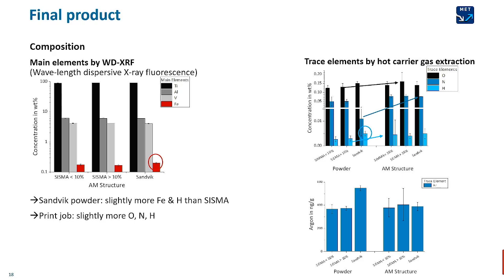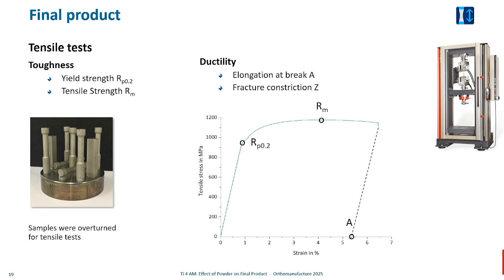And after the print job, we had some small differences. So hydrogen was increased for the others as well after the print job. Oxygen was slightly increased in some cases, or nitrogen in others. So we've seen quite some differences in the composition, but what's the effect on the mechanical properties, which is at the end the most critical parameter.